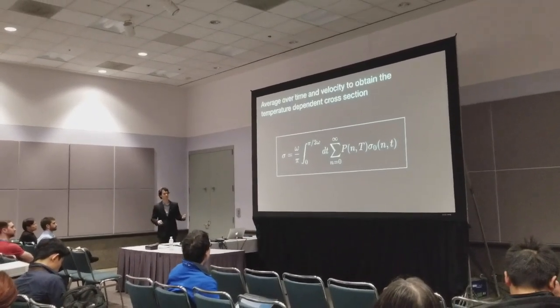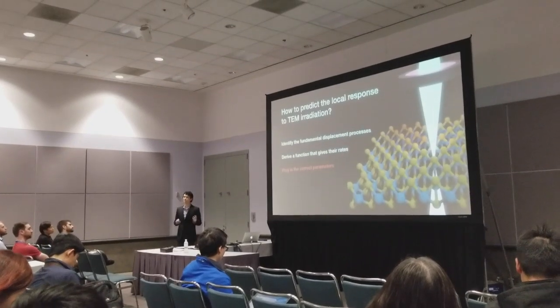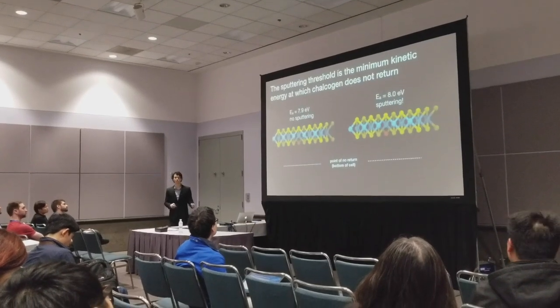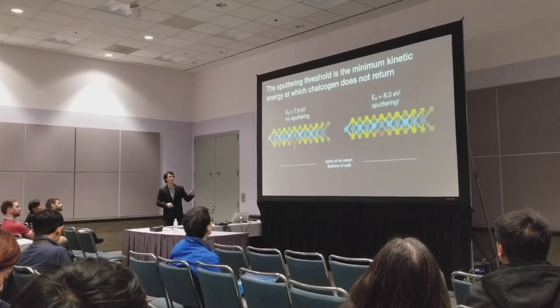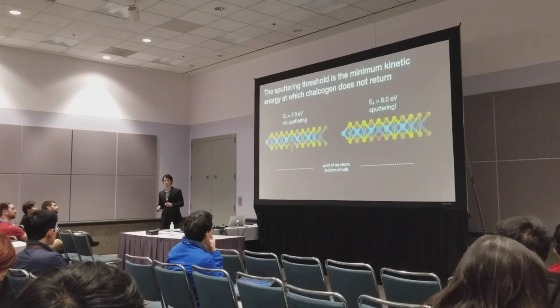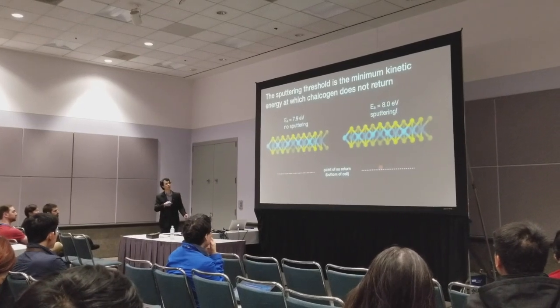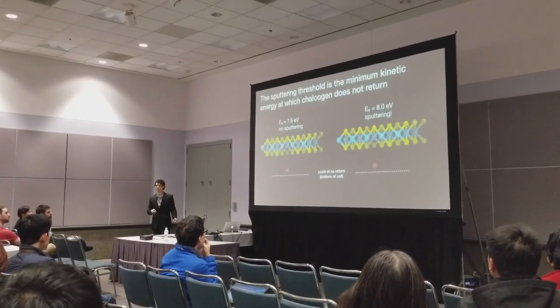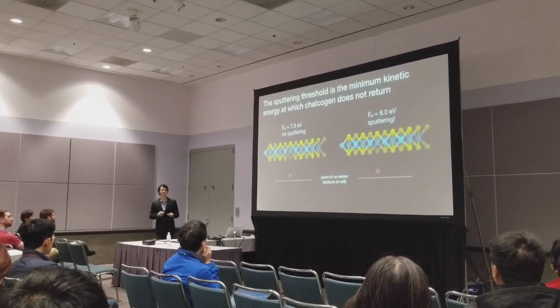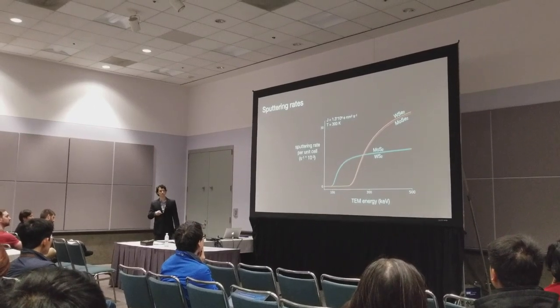All that's left is to find the displacement thresholds for migration and sputtering and plug them in — we do that using DFT-based molecular dynamics. The simulation for sputtering is straightforward: we send an atom away from the crystal with some initial kinetic energy. If the atom returns, that energy is less than the sputtering threshold; if it doesn't return, the energy is greater. We find that the sputtering threshold for WS2 is somewhere between 7.9 and 8 eV. The sputtering thresholds for MoS2, MoSe2, and WSe2 are fairly similar. We then plug in these sputtering thresholds to plot sputtering rates as a function of TEM energy.